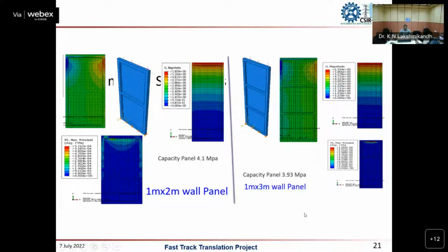So this is a basic fundamental study we did, and found that the ferrocement wall has the capability of carrying whatever load comes to the system, at least for G+2. These are the experiments we did for the G+2 structures, and we found that it is suitable. But the problem we are facing is the thin system, because it is a 20 mm or 25 mm thick wall, which does not have sufficient thermal or sound insulation. So we want to keep this in mind.